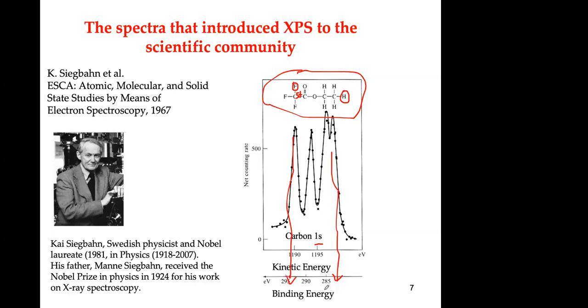So you have two ways to do this. You can plot against binding energy or kinetic energy of the electron, but the most common one is binding energy. I will show you later on some spectra plotted with respect to kinetic energy. And as I told you yesterday, the binding energy will be more or less equal to the energy of the source, h nu, minus the kinetic energy that you determine for the electron. And there is another term, phi, the work function, and other parameters that you have to correct for. But the main part is the kinetic energy and the energy of the source.